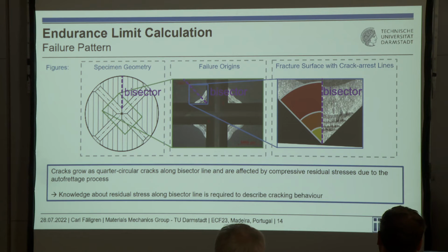And they are affected by the compressive residual stresses introduced into the component after autofrettage. So exactly on this bisector line, the residual stresses are the highest, and they affect this quarter circular crack path and make it more like a butterfly wing shape. So basically the knowledge about the residual stresses along this bisector line is required to describe how, or to calculate how, these specimens fail.